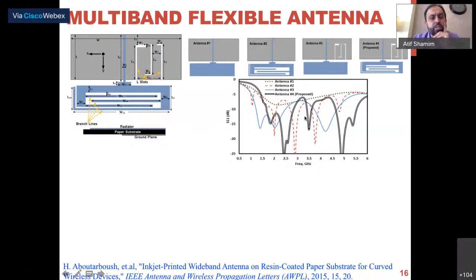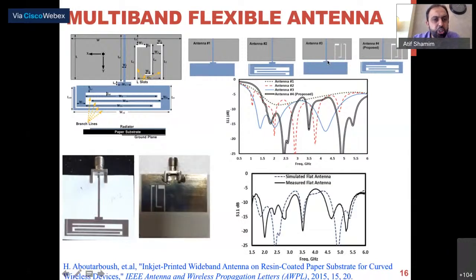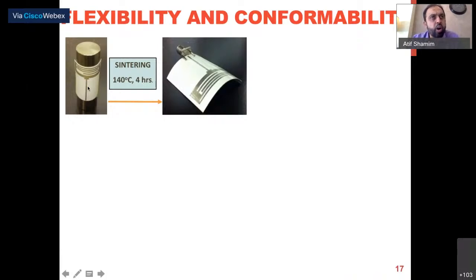So the conventional paper, which I'm showing you, is like a photo paper and has a polymer coating on it. So when we heated it, we realized that whatever shape you heat it to, it retains it. The reason is that there's a polymer coating which will basically get hardened, so it retains the shape, which is good for conformal applications. So for example, if you want to put an antenna on a human arm, or on a pole, you know the radius, you could basically heat it in that fashion.